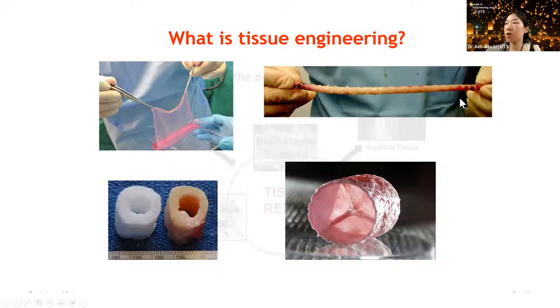This is a blood vessel. So it is an artificial blood vessel that contains a natural polymer called human elastin. Elastin is a molecule that we find in our body, but we don't make any more of this as soon as we're born. And that is a really big challenge for tissue engineered organs and tissues that need to have an elastic component, like your blood vessels, like your arteries, your skin, etc. So there is now a method to purify human elastin by expressing the gene in bacteria and then incorporating human elastin into structures like blood vessels.